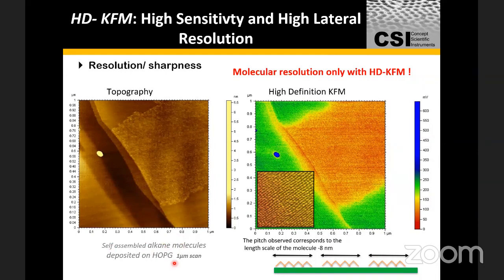So here, what you have is a self-assembled alkane molecule that has been deposited on the HOPG. Now if you look at the resolution that you get with the Kelvin probe microscopy, you can see that you're actually able to image the molecular nature of the alkane deposition itself. This is not a topography image, this is the electrical image. So you're really able to capture this down to a resolution of, and what's the length scale here? Yeah. So each of these alkane molecules are about 8 nanometers.